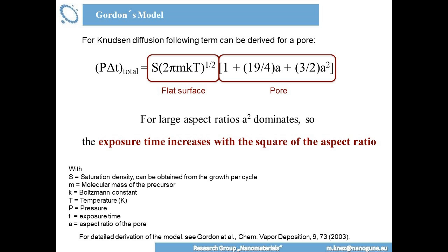That means the time which you need to expose your substrate to the precursors scales with the square of the aspect ratio. And this is very important to know because people sometimes really tend to think it's a linear relation. It's not. It's a square relation. That means you will have an enormous extension of time just by increasing the pore length a little bit. And you need to keep this in mind, otherwise you will never have a really good coverage there.